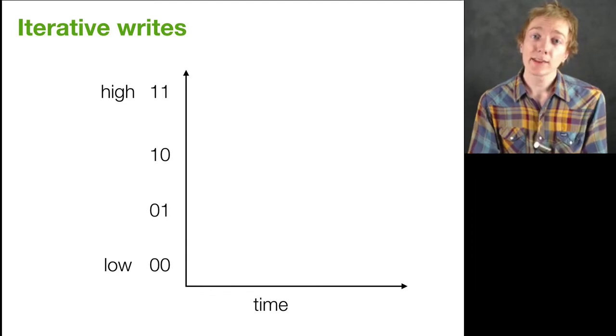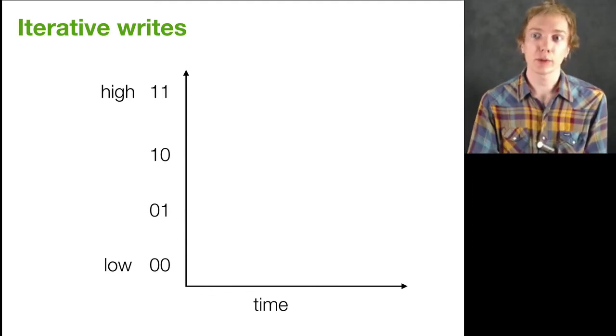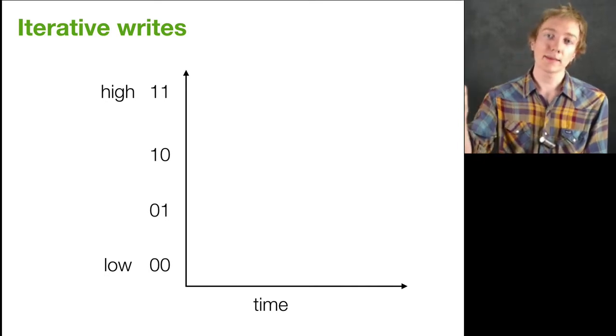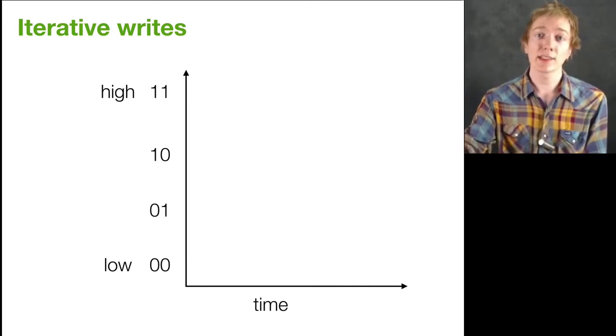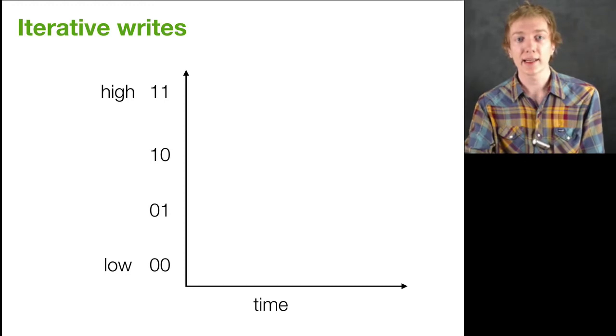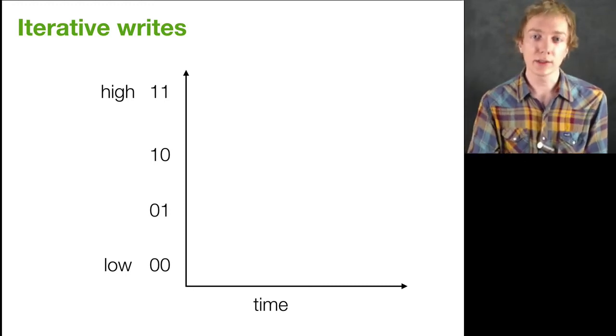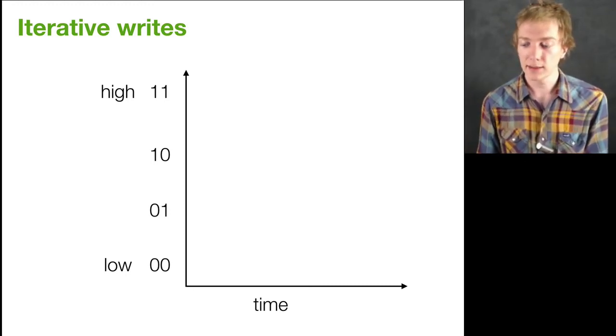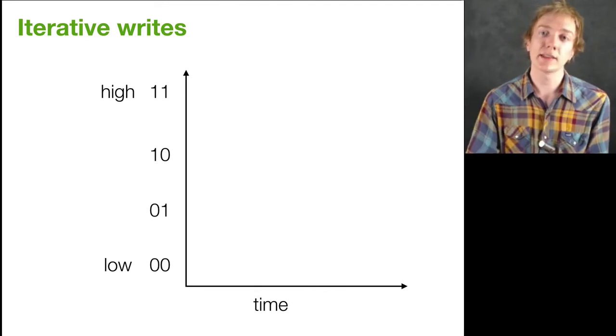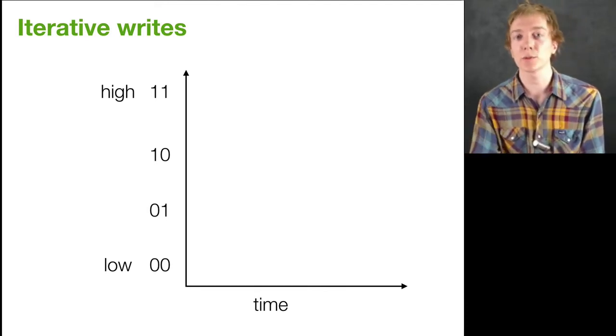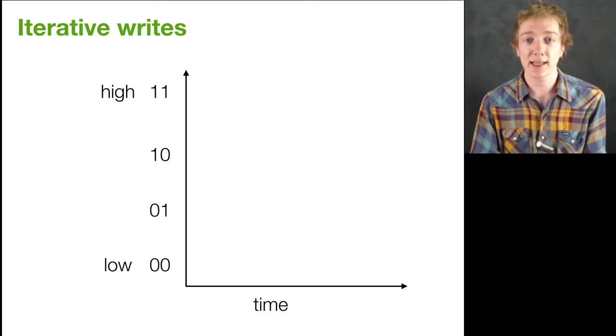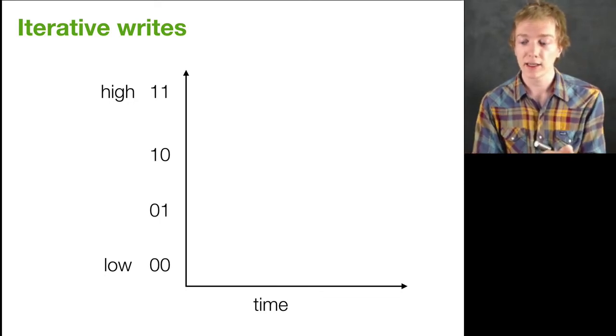The way that the writes work in typical multi-level PCM cells is using an iterative approach. That is, each individual write pulse that you can send to a PCM cell is not accurate enough to set a desired level to a desirable accuracy in a PCM cell. So systems use an iterative approach. They'll send a write pulse, read the value back, and if it's not close enough to the desired target value, then you'll write again, either increasing or decreasing the resistance each time.